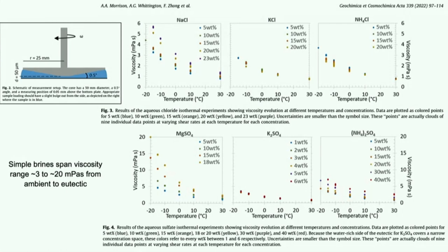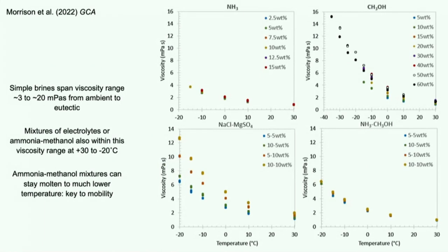So first of all, the units here are now all millipascal seconds. Water coming out of your tap is 1 millipascal second. And so we're looking at a range of, for these brines, probably between about 3 and 20 millipascal seconds, going from ambient temperature down to the eutectic temperature, which for most of them is around minus 20-something degrees C. So we have a range now of maybe a factor of 6 for the liquids.